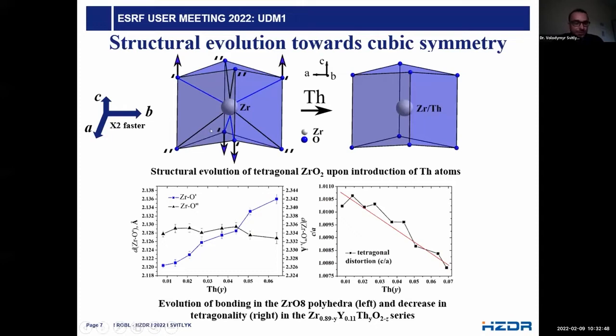And how does it happen? Actually, it's possible because of a strongly anisotropic lattice response to incorporation of thorium. In fact, in the ab plane, the lattice exhibits twice as fast an expansion as in the orthogonal c direction. And also, when you introduce thorium, you decrease the tetragonality of the system. So the tetragonal distortion, you see the c/a ratio, is decreased. So there is a clear tendency towards a higher cubic symmetry.